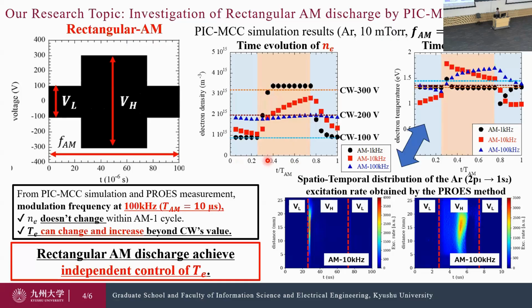At a relatively low modulation frequency of 1 kilohertz, the electron density exhibits temporal variations, whereas at 100 kilohertz, it no longer responds to the amplitude modulation. In contrast, the electron temperature significantly exceeds the CW discharge value during AM discharge. And this electron heating effect is observed even at 100 kilohertz.